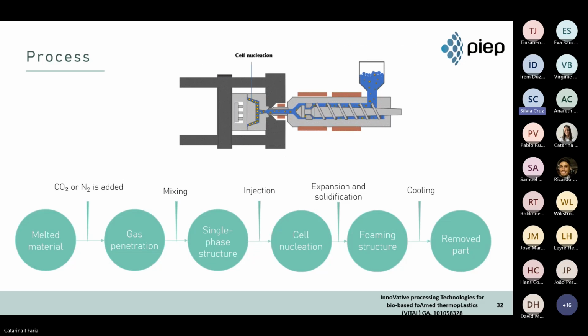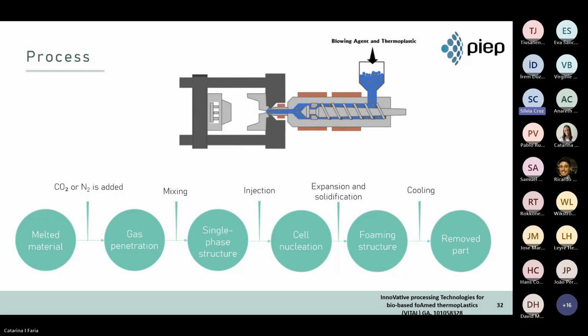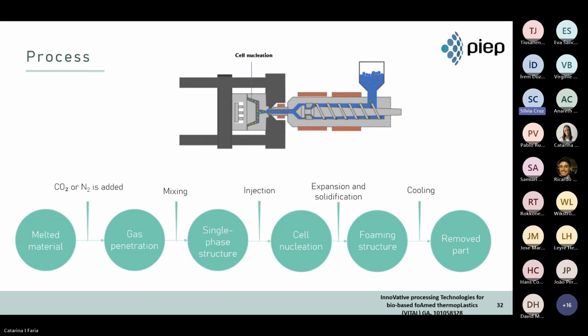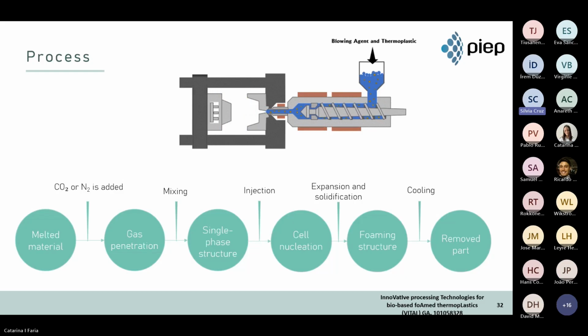After the material passes through the injection system, the pressure drops quickly, causing high thermodynamic instability, leading to the precipitation of the gas phase out of the polymer, initiating the cell expansion. The high pressure and temperature characteristics of the injection molding process will guarantee that the physical foaming agent maintains its supercritical phase until the material is injected into the cavity.